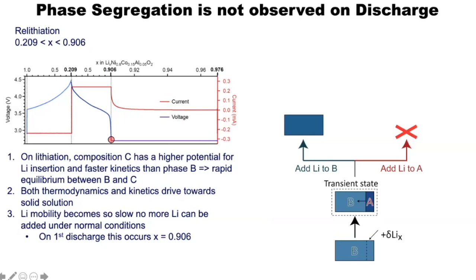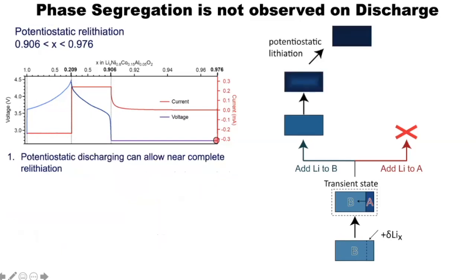So on the way back, you've got a phase B, and remember, this is the phase that has rapid lithium mobility. And as we're starting to put the lithium back, the lithium is now almost completely full. You can imagine again this surface state that's almost lithium 100%. But because phase B has rapid lithium mobility, you can actually get much more rapid equilibrium. And so you can continue to add lithium into this material until you finally hit this state where the lithium mobility is too low. And so kinetically, you can't get more than about 90% of lithium into the material.